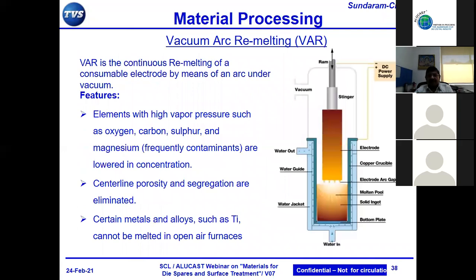And you take an ingot out of an ESR furnace, and then you have to go through a VAR, vacuum arc remelting. This is where you remove elements like oxygen, carbon, sulfur, all these contaminant elements are removed by vacuum. It is a very high vacuum, almost about 10 to the power of minus 6 torr. And this vacuum furnace is again a water cooled copper crucible. The limitation on the diameter of this particular electrode would be a maximum of 1 meter. So with a combination of ESR plus VAR, the maximum melting diameter of the ingot would be 1 meter.